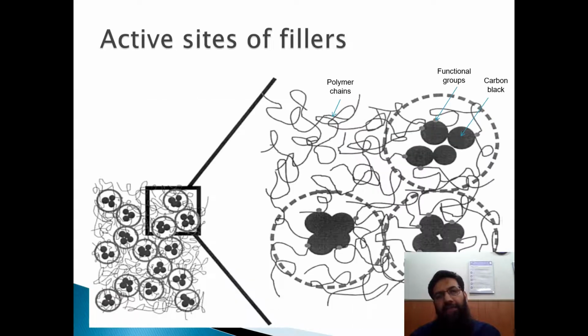So if we use these active sites during the compounding of the different polymers, you can see here, I take the example of the carbon black. When carbon black is mixed with the different polymer chains, the presence of these functional groups or active sites, they interact with the chains of the polymers. And when they interact with the chains of the polymers, it will have the better interaction between the filler and the polymer. So it would give you the better mechanical properties by the reinforcement mechanism of filler and the polymer.